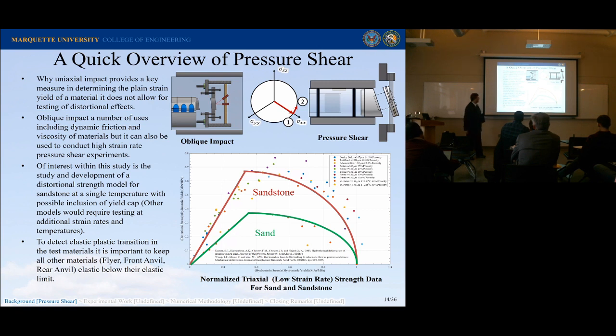The other thing that you can pull out through these pressure shear tests is you get these caps, and you get this pressure distortional stress. If I just was to pull on it in uniaxial, I would just pull out these values down here, which wouldn't be as cool as mapping out an entire hydrostatic distortional stress regime.